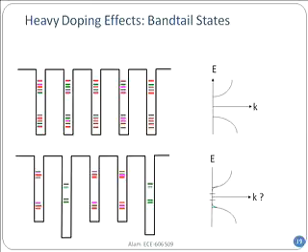These are called band tail states, because they stay slightly below, but now there is a continuum, because the donors can talk among themselves, but fewer, right? Donor atoms are still 1/10, 1/100th. So it's fewer than the normal density of states, but no longer completely negligible, no longer just one level like a trap or a dopant as I was showing you before. This EG1 and EA1, remember those levels? Those levels are no longer one level. It is a continuum now.